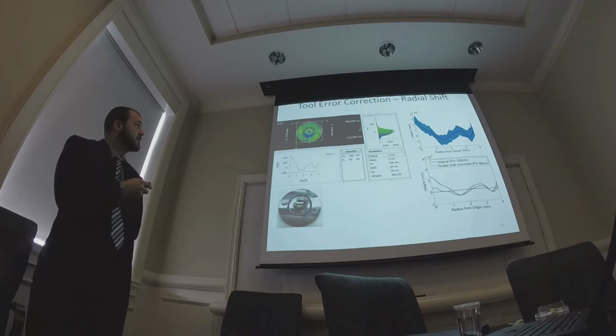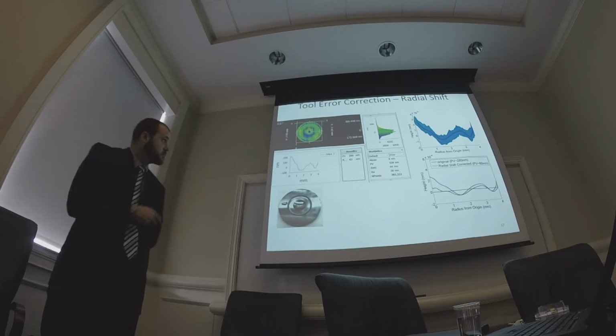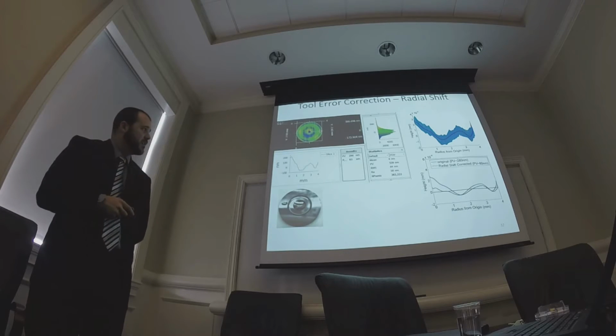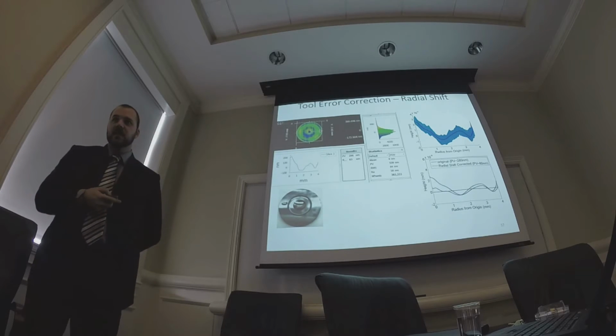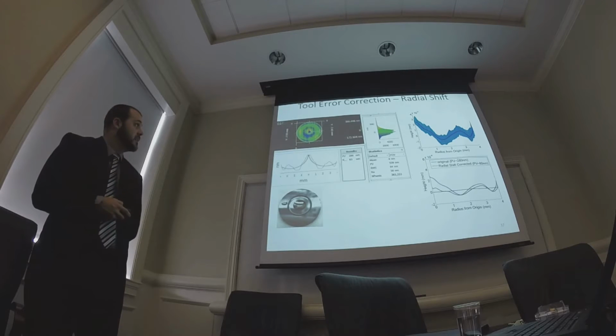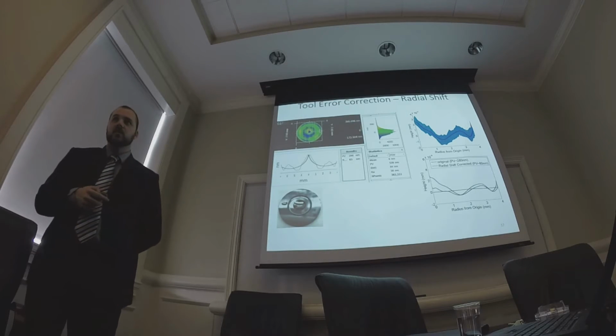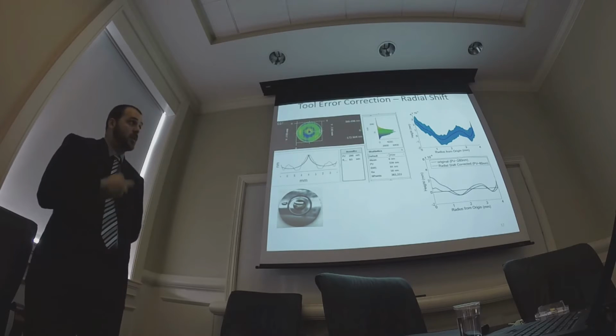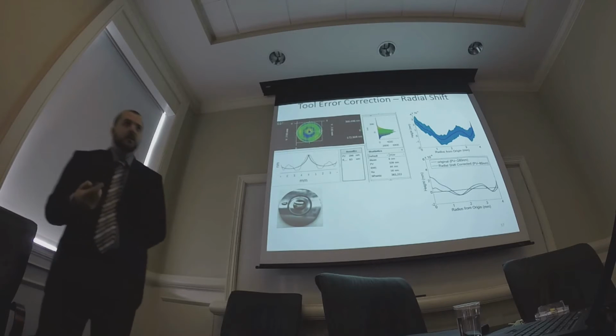If we average or display all of the data points with the radial distance out from the center, and then add that error, we get this shape here. So at first glance you may not think that's an M or a W, but it's actually a W with waviness superimposed.